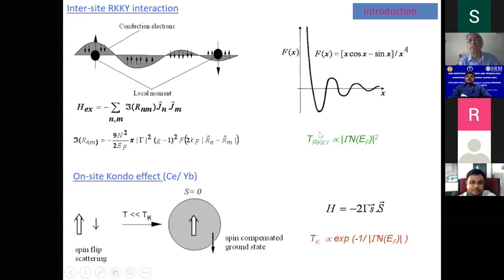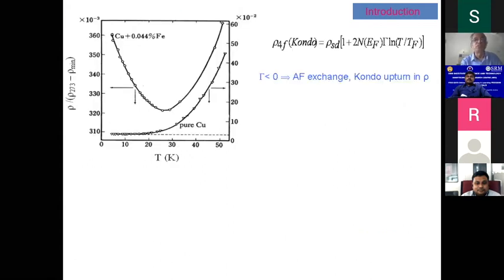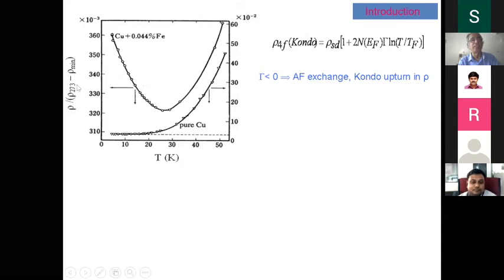This is the Kondo temperature. Therefore, when you have a single site, a single atom or a single cerium, you have only this interaction. When you have a number of cerium atoms, a number of rare earth atoms in a lattice, then you can have the other interaction too. These two, the single ion interaction and the lattice interaction, can compete and make the situation complex. Now, what is the Kondo interaction? It was first actually observed for very small doping of iron in copper. If you look at resistivity, it goes logarithmically with decreasing temperature. This is electrical resistivity of copper metal; at low temperature there is an upturn here. This is the signature of the Kondo effect.